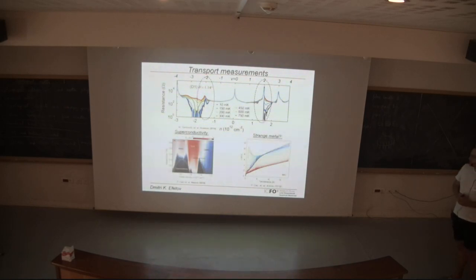And the funny thing is, we can characterize the device and define how many electrons we have loaded per Moiré unit cell. We start at the charge neutrality point, where we have this resistance peak and have loaded 0 electrons per unit cell. We can load 1 electron per unit cell, 2, 3, 4, and do the same thing on the hole side. And where we find the strongest variations of the resistance is around filling -2 and filling +2. These are exactly the regions which I explained in the beginning, where superconductivity happens, where correlation effects happen, and where also the strange metal phase occurs.